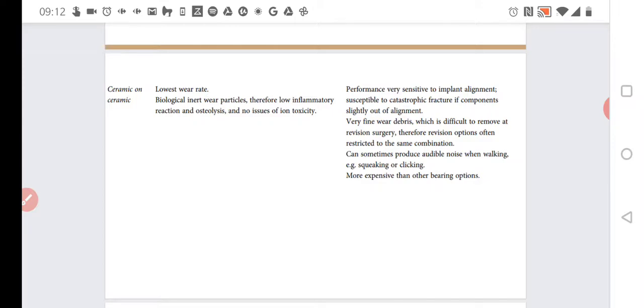However, there is one con: fractures. These are brittle materials. And this brittleness can cause complete failure of the endoprosthesis. Because of this, the performance is very sensitive to implant alignment. There may be some very fine wear debris which is difficult to remove in revision surgery. Therefore, revision options are often restricted to the same combination. Can sometimes produce audible noise when walking, like squeaking or clicking. And generally it's more expensive.